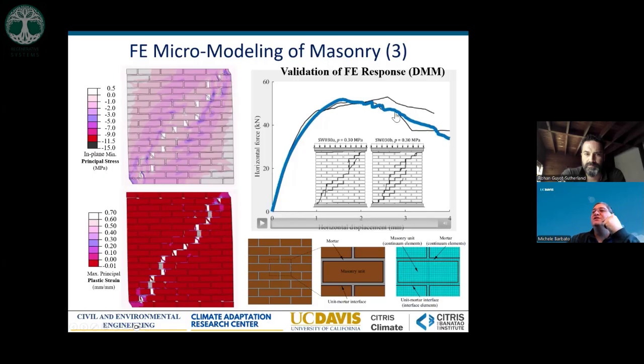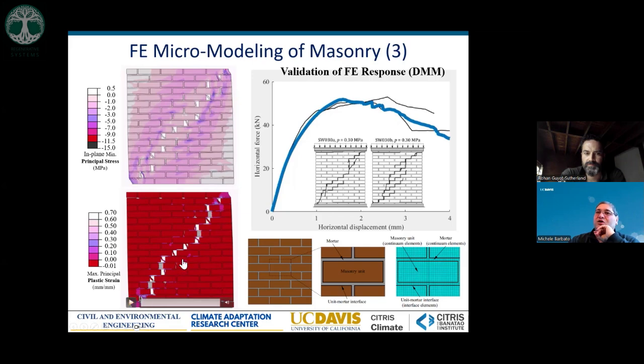Now, in addition to having this very nice correspondence between the horizontal force and horizontal displacement globally for our walls, we also had a very nice matching of the cracking pattern of our numerical model with the cracking pattern that was observed experimentally. If you look at the open spaces in these red figures here, those are where the cracks form and where there is separation of the blocks. You can compare it with the dark lines in the experimental results here. And you can see that we are capturing not only the global behavior, but also the local behavior and the formation of cracking. So we found that these results were pretty good with all of the different models, including the simplified and the detailed micromodel that we developed.